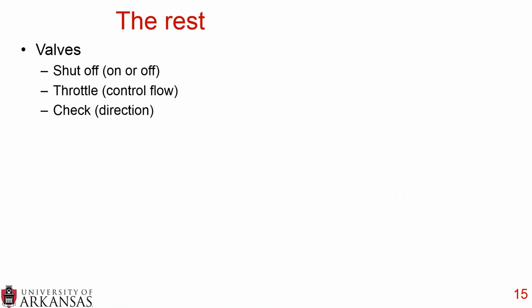For the rest of the transfer devices, for valves, there's 3 types of valves you can have. You can have a shutoff valve, and these are either on or off. There's no in between. It's binary, black and white, shut or on. You can have throttle valves, and this can control the flow. So a throttle valve, you can usually turn at some sort of angle, so you can have anywhere between completely on to completely off, or you can have about 45% flow. You'll often see those around mills also to control the flow going into the mill. And then you can have what's called a check valve.